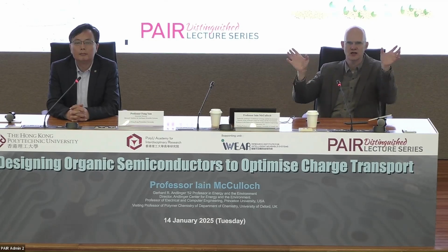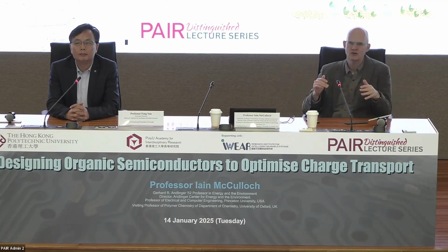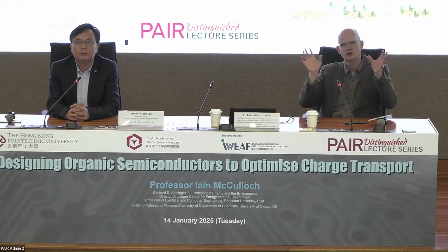But in most cases you can design that in such a way that that won't happen. You're going to use solvents that are outside the solubility parameter of the layer below. There's usually a solvent you can choose, because anytime you have post deposition chemistry, you typically lose in every aspect. You lose because there's local disorder that you're introducing due to a chemical reaction.